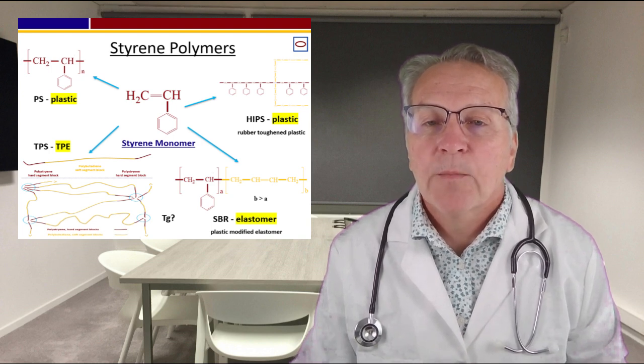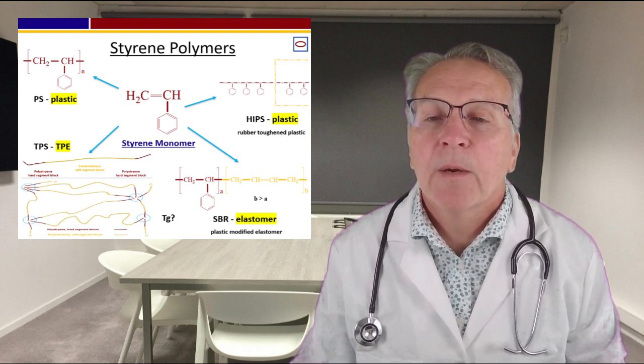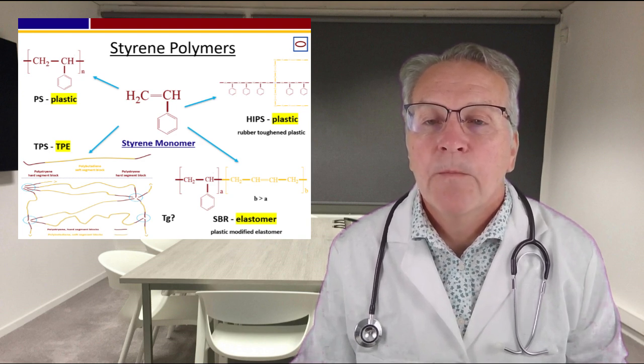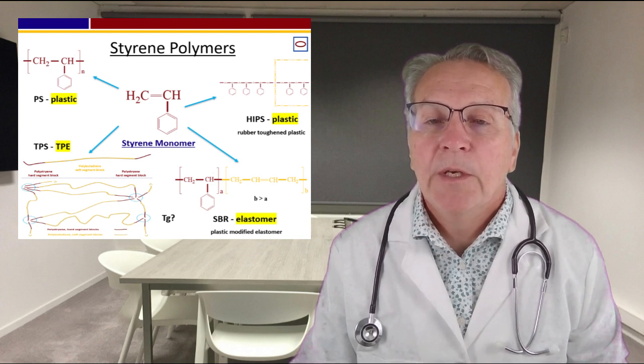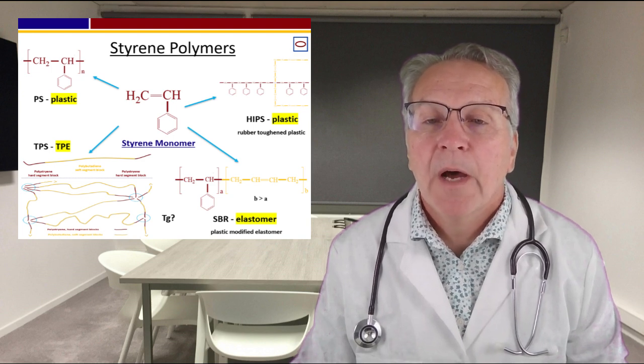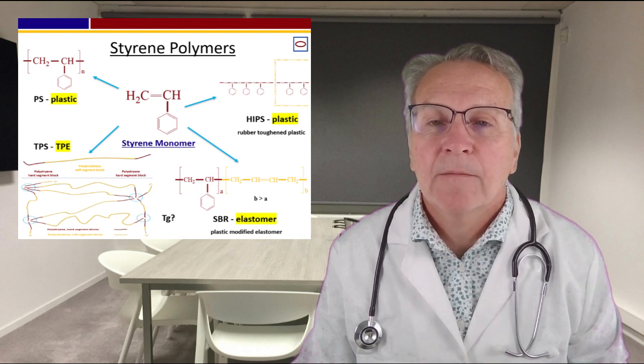We know amorphous plastics have Tgs above room temperature, and the Tg of polystyrene is about 100 C, while the Tg of elastomers is below room temperature, with the Tg of SBR being about minus 60 C. We talked in a past That's Working Knowledge video how a flexible and asymmetric repeat unit like butadiene will need low temperatures to freeze out and become glassy.